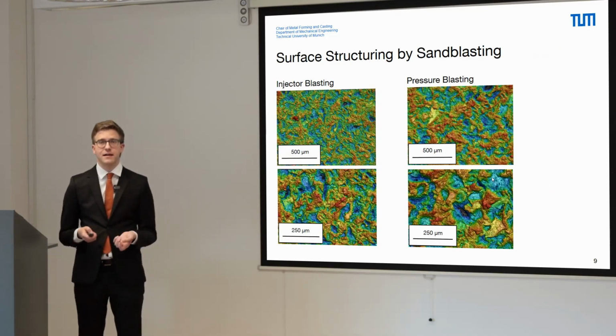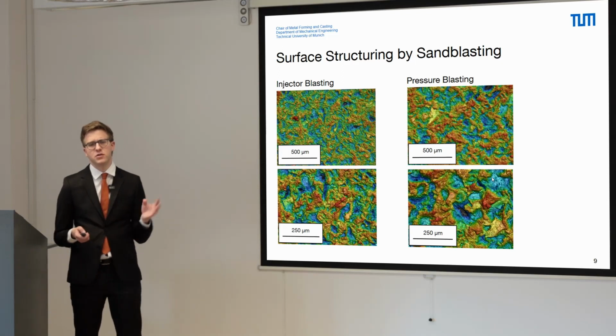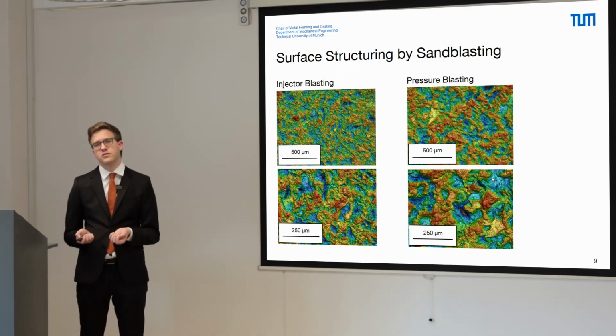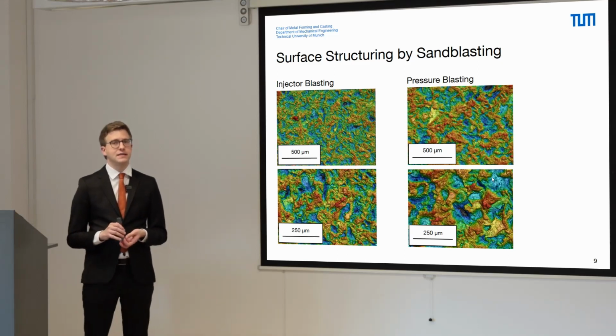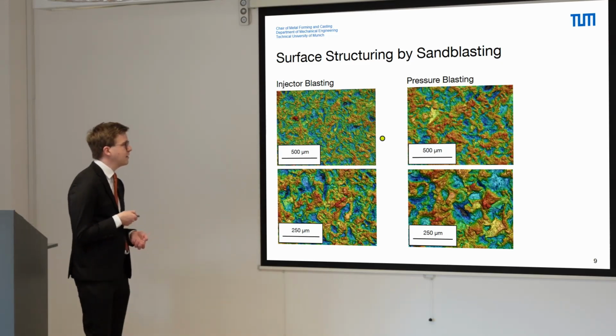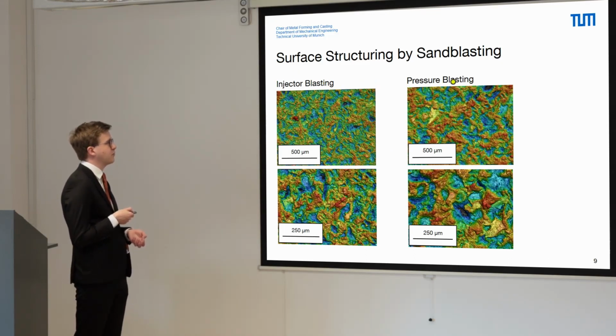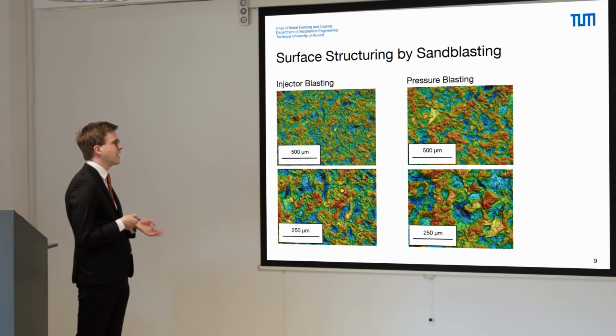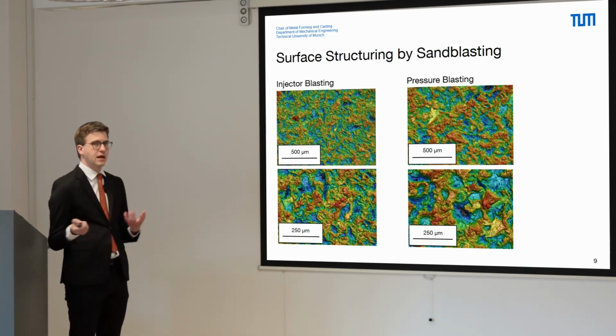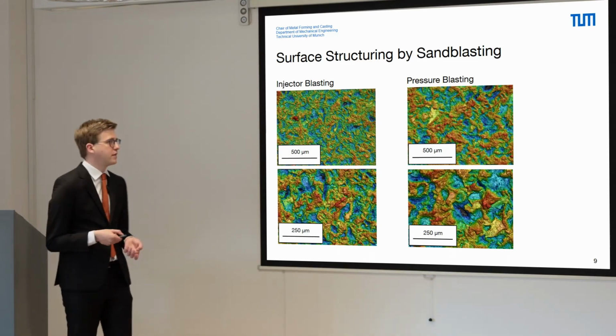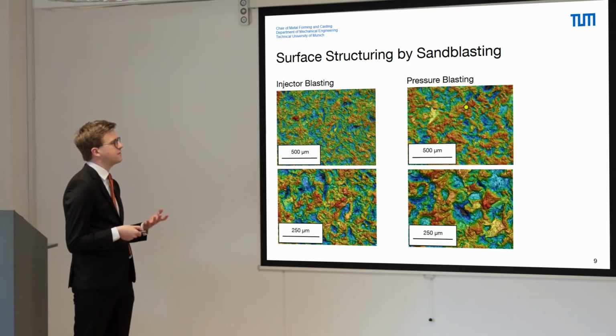When we analyze the resulting surface structure, we see certain differences between the laser structuring and the sandblasting structuring. Let's start with the sandblasting structuring. On a microscopic level, we can see, both for the injector blasting and the pressure blasting at two different magnifications, that we achieve more of an irregular, sharp-edged surface structure. The difference is that the pressure blasting uses a higher amount of pressure, so the result is a more structured surface and a larger surface roughness increase.